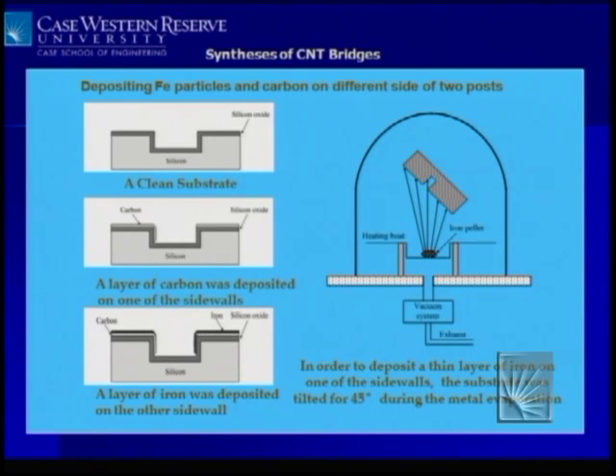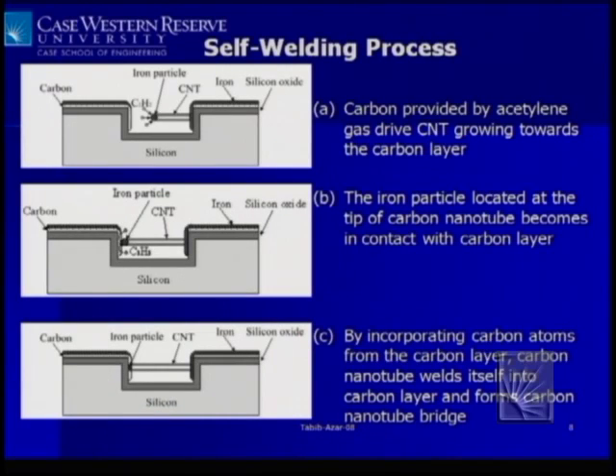So these are the posts that I showed you. What you do is on one wall you deposit carbon, and on the other wall you may want to end up with iron. That's your catalyst. The way you do this is by tilting the sample over some kind of heater where you put your iron pellet or your carbon source and evaporate. And you use these different walls to do shadow masking. That way you can end up with different materials on different parts of the device. And you can do this across a wafer, so it is very scalable.